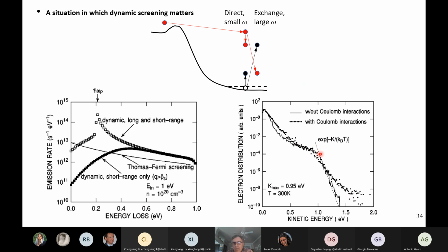But then when you reach the point at which the electrons have reached the applied bias, in this case 1 electron volt, 0.95 actually, in this particular case, from then on the distribution function has a decay which is the room temperature decay. Clearly, it's related to the equilibrium distribution function that we're assuming. But the exact details of why this is so remain a little bit of a mystery. I mean, you find it in Monte Carlo simulations, everybody does.